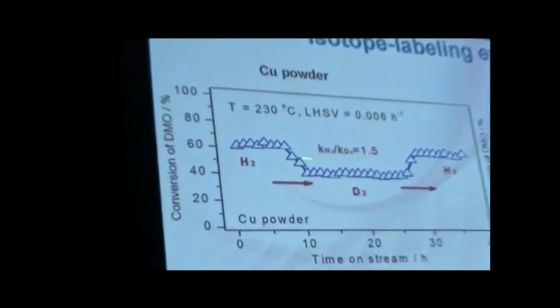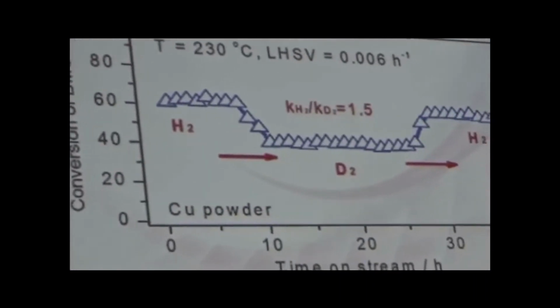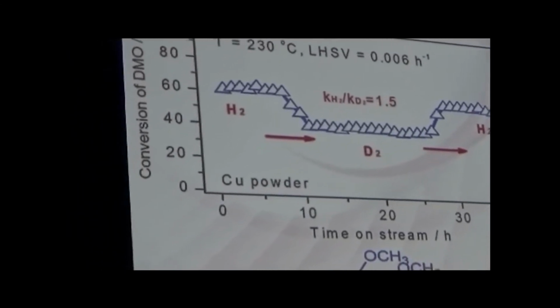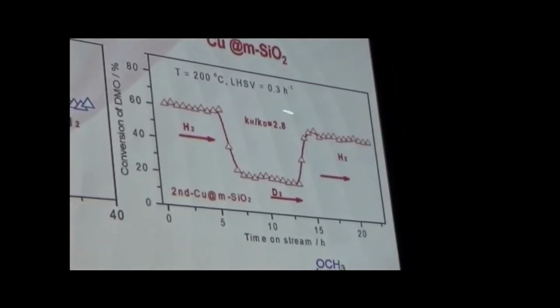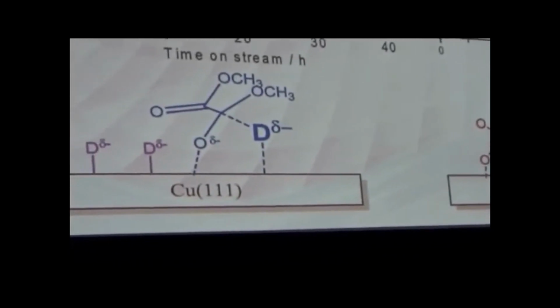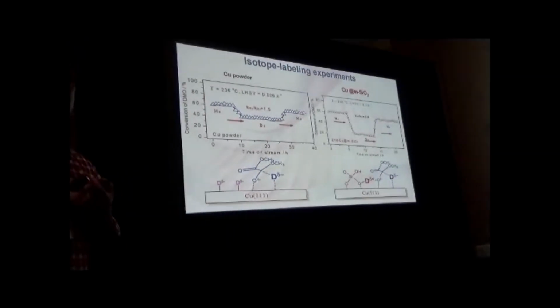We also have the KIE value. For the pure copper powder system, the KIE, the kH2 to kD2, is about 1.5. But on the silica copper system, the KIE value is about 2.8. This is almost two-fold larger. A different KIE means a different mechanism. Why in this case do we have a large KIE? Because in this case, not only one deuterium participates in the transition state, this one also participates in the transition state. So this involves the large KIE.